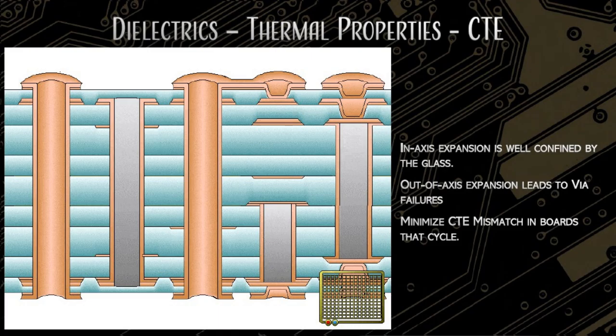So one of the issues that we have to look at is the coefficient of thermal expansion. The reason for that is that copper constrains the fiberglass. It keeps it from stretching out. Fiberglass is relatively well constrained in the X and Y directions, the in-plane directions, but it's poorly constrained in the out-of-plane direction, the Z-axis direction.